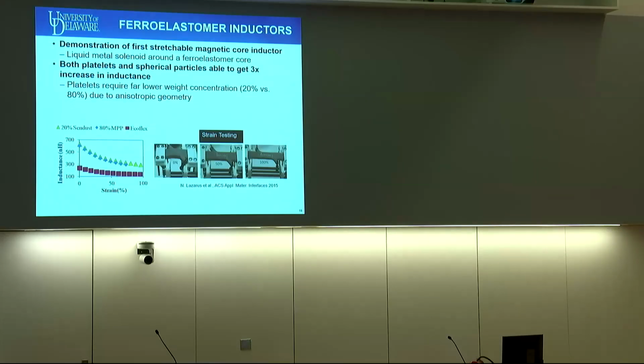But based on this, we demonstrated the first stretchable magnetic core inductor, using a liquid metal solenoid around a ferroelastomer core, and found that in both cases, we were able to get a sizable magnetic response. So about a factor of 3 increase in inductance. This means about a factor of 3 increase in the magnetic permeability of the material. We also found that because the platelets short out the elastomeric material more efficiently, you can get that factor of 3 increase at a lower weight concentration. So about 20% versus 80% for the more spherical material.